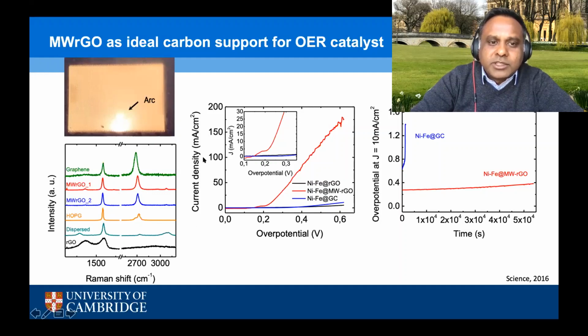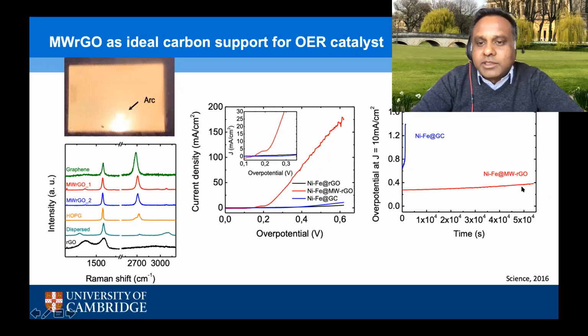So what this shows is current density as a function of overpotential. And we can see that the reaction starts to proceed, which is indicated by this red curve, at a much lower overpotential when the catalyst, in this case nickel iron layered double hydroxides, is put on microwave RGO. We can see that the overpotential of the reaction is decreased quite dramatically relative to other forms of carbon. And this is because this microwave reduced graphene oxide is more conducting and leads to more intimate contact between the catalyst and the support. But not only that, having the right support also allows us to increase the lifetime and stability of the catalyst for this reaction.